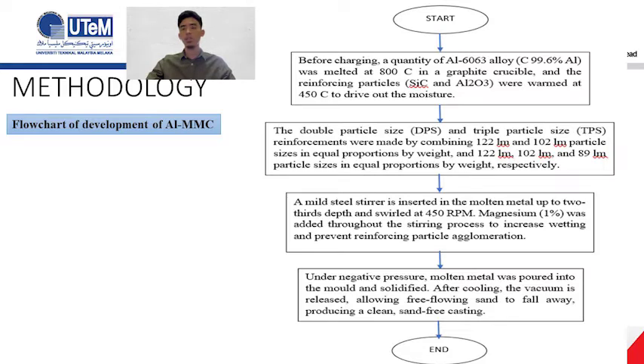And then magnesium 1% was added throughout the stirring process to increase wetting and prevent reinforcing particle agglomeration. The last step is that, under negative pressure, molten metal was poured into the mold and solidified. After cooling, the vacuum is released, allowing free flowing sand to fall away, producing a clean and sand-free casting.